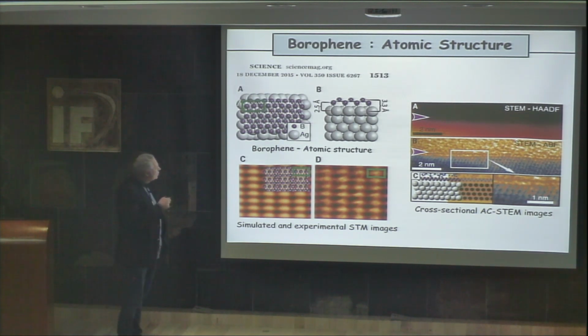And they proposed a model for this borophene structure. So the borophene structure, as you can see here, has a triangular lattice like this, and it's a little bit buckled, as for example the case of silicene and germanene that I showed you just before. So these STEM pictures have clearly shown this buckling, and in fact, when you look from the top, you have a perfect agreement between the STM image that you obtained experimentally and from the atomic model here.